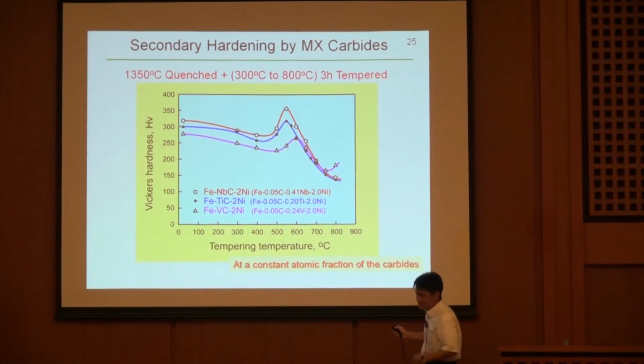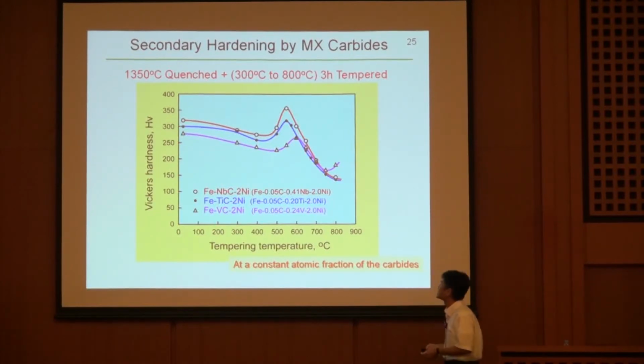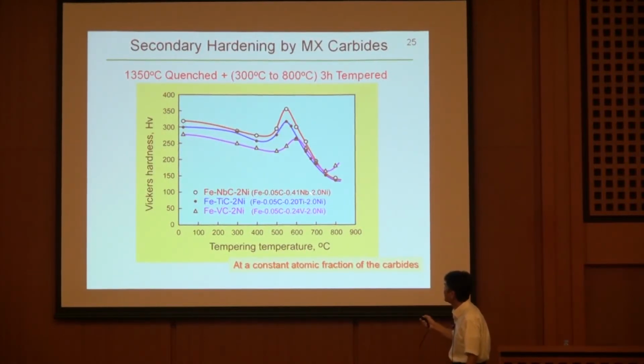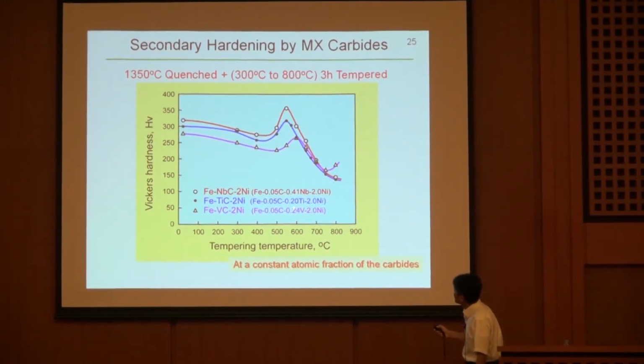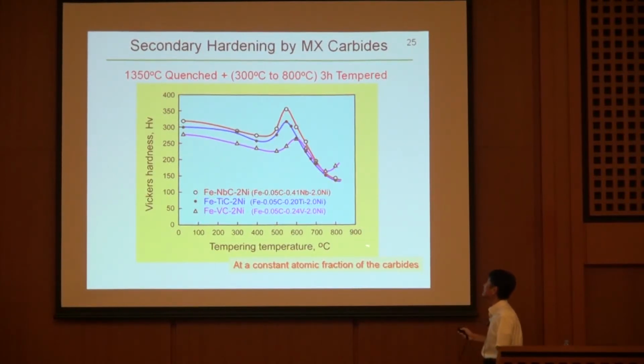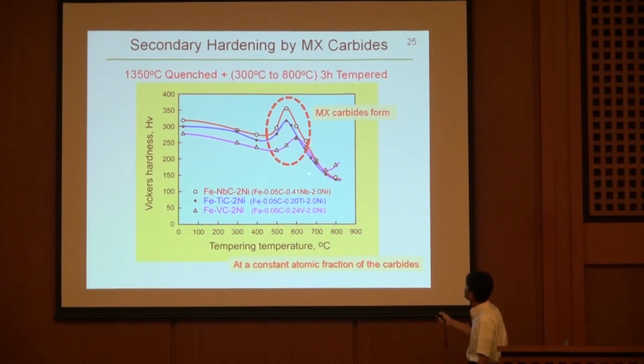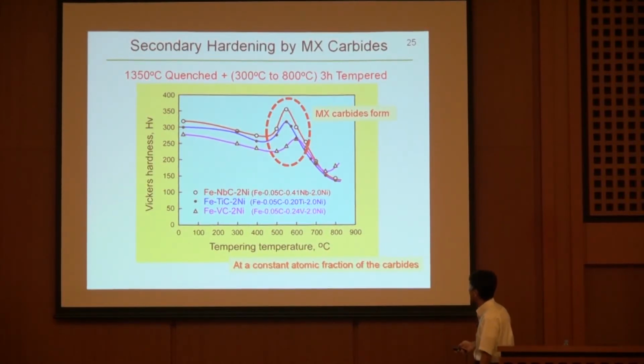This is because our aim is to clarify the mechanism. So I have to say they are not engineering steels in this case, okay? Model steels. And the chemical composition has been chosen to obtain a constant atomic fraction of carbide. And here, when the secondary hardening occurred, you have MX type carbides.